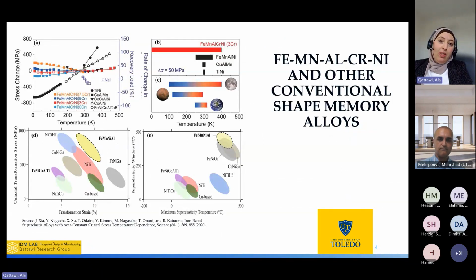Other studies have also been done, particularly on this iron manganese nickel aluminum alloy system, for high temperature applications or applications where there's a high variation of temperatures, for example, aerospace or space exploration. And you can see there is a window where this alloy system potentially can perform with a transformation temperature and strain that's actually very good and desirable. So certainly there is a window and a potential for exploring these alloy systems.